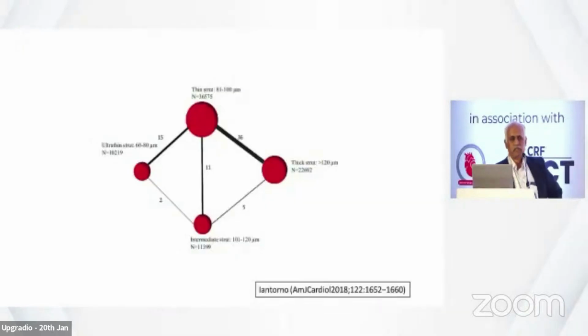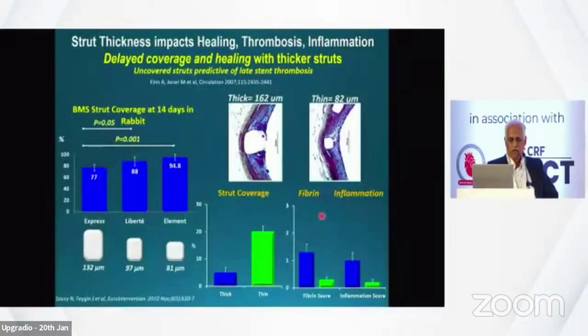Now, the strut thickness becomes an issue. The strut thickness in the early stents used to be more than 150 microns. But now we have got ultra thin struts, about 60 to 80 microns. So does it matter what the strut thickness is? It does matter. Why? Because if you have got a thicker strut, it takes more time for the strut coverage to occur. If strut coverage is delayed, there is an uncovered stent with fibrin formation and inflammation. So the thicker struts take more time and they are prone to thrombosis.